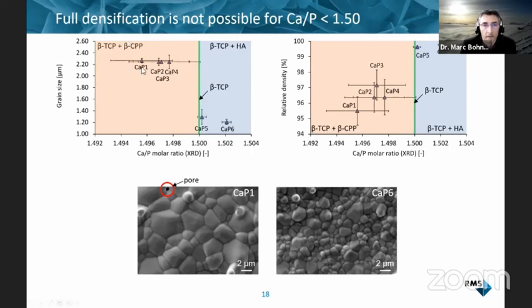We named them CaP1 to CaP6, and they vary in terms of calcium to phosphate ratio from 1.495 up to 1.502. Here you have about 1% pyrophosphate, and here about 1% hydroxyapatite. So all these beta-TCP powders are over 99% pure, so a highly pure sample. And you can see that there's a clear shift of the grain size and also the relative density at this level of 1.5. If you look at SEM, you see the shift of grain size between below and above 1.5.